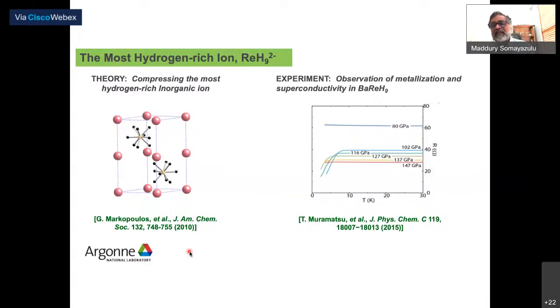There is a whole class of materials, I will not go into that, which is barium rhenium hydride, sodium rhenium hydride, lithium rhenium hydride, and so on, which again are telling you with respect to that simple-minded periodic table I showed you, that you have these light elements like sodium, lithium in them, and the hydrogen, and the intermediate being a rhenium. And so after some amount of work, we realized how to synthesize these materials and load them in diamond cells and do these transport measurements at increasing pressures. In fact, I remember that this was in the early days when I actually gave a physics colloquium in BARC and I was talking about this.